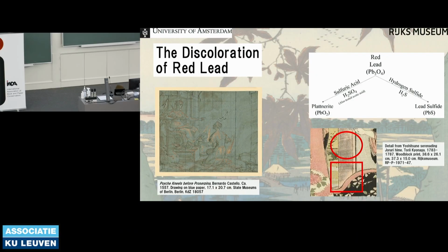So, lead-based pigments are known to discolor. Infamously, in Western art, white lead is known to turn gray and blacken over time. Red lead is also observed to similarly change color, and this discoloration can change from brown to black to a metallic silver color. This is believed to be the formation of potentially two different products, either the formation of plattnerite through the exposure to dilute sulfuric acid by way of atmospheric pollutants, or through the formation of lead sulfide through the exposure to hydrogen sulfide. This is the same reaction that causes the discoloration of white lead, but in red lead, it's known to take place at a much slower rate.